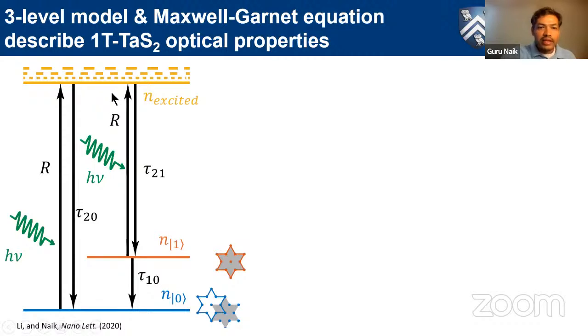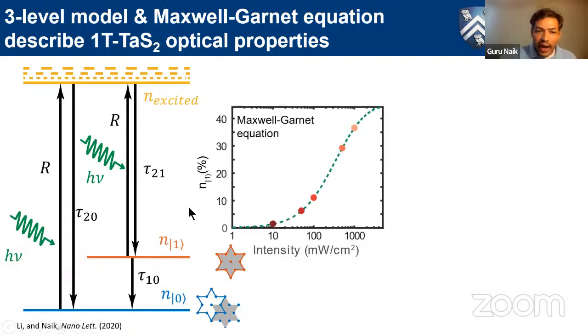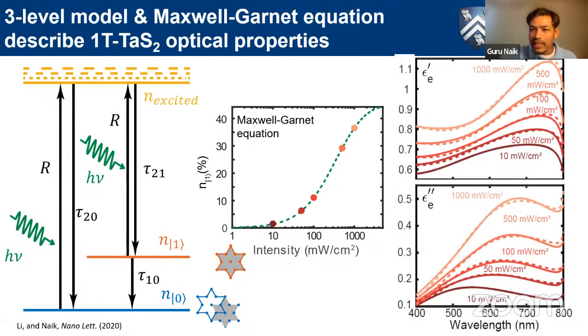To test this, what we did is simply build a 3-level model, where we have this upper level stacking and lower level ground state stacking shown here, and then we have light causing all the transitions. The key time constant is this one, which we measure from experiments. Using that, we can predict what fraction of CDW domains exist in this higher level stacking. Then we use a Maxwell-Garnett effective medium theory to predict what the optical constants should be at any of these intensities, and then we see how they match with experiments. And the matching is quite remarkably good. And this has, in fact, no free fitting parameters. We're really surprised that it actually does so well.